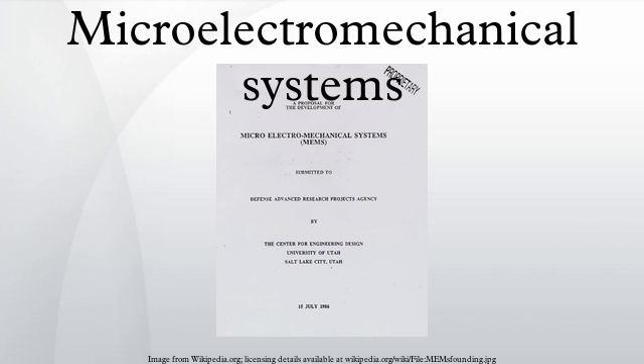If the ions have high enough energy, they can knock atoms out of the material to be etched without a chemical reaction. It is a very complex task to develop dry etch processes that balance chemical and physical etching, since there are many parameters to adjust. By changing the balance, it is possible to influence the anisotropy of the etching. Since the chemical part is isotropic and the physical part highly anisotropic, the combination can form sidewalls that have shapes from rounded to vertical.